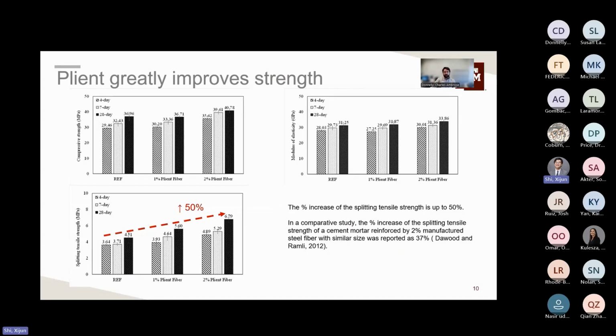In a comparative study, the increase in splitting tensile strength was compared between the Plient concrete as well as concrete reinforced with the manufactured steel fibers. And it was found that using a manufactured steel fiber with a similar size reported only a 37% increase in the splitting tensile strength. So again, not only are the Plient fibers improved compared to standard concrete, but they also show improvements compared to currently on the market manufactured steel fibers.